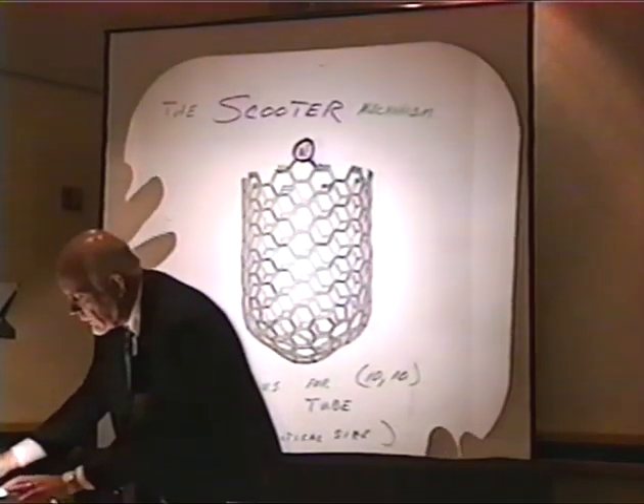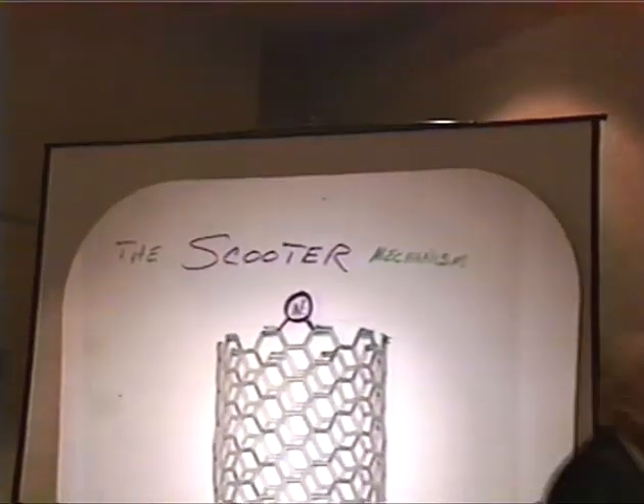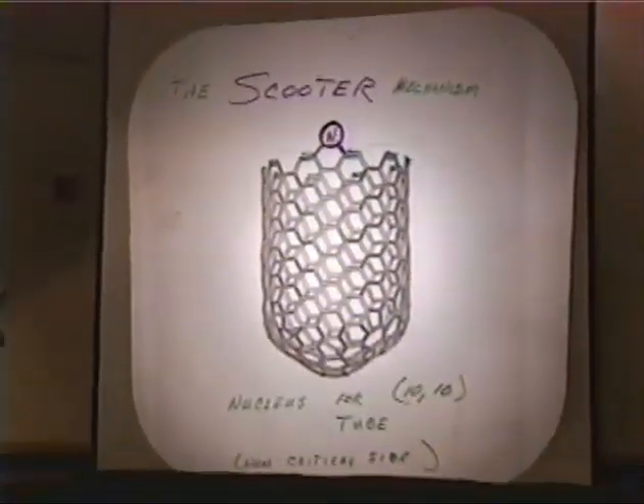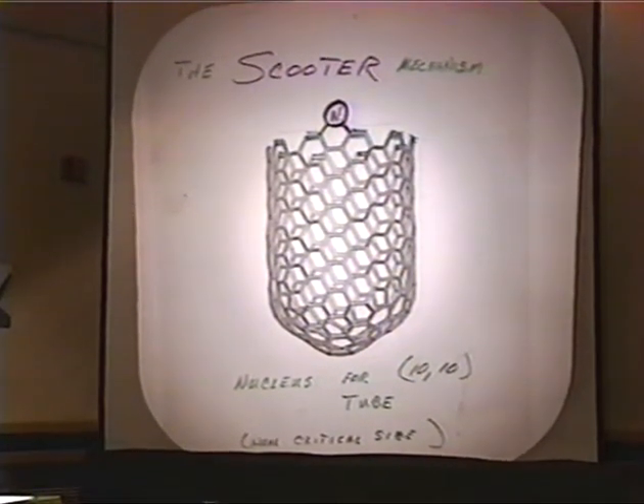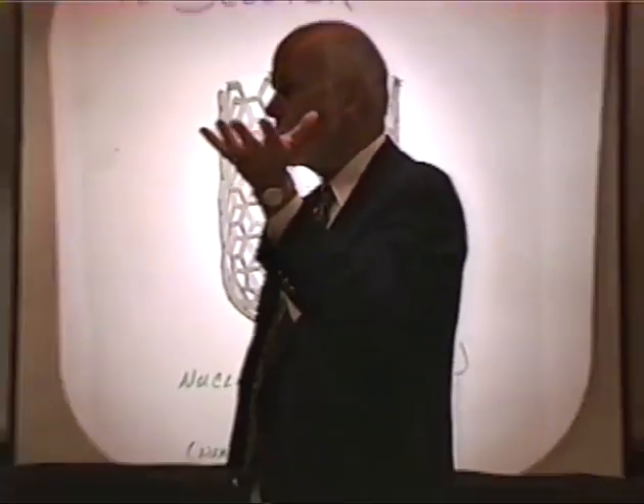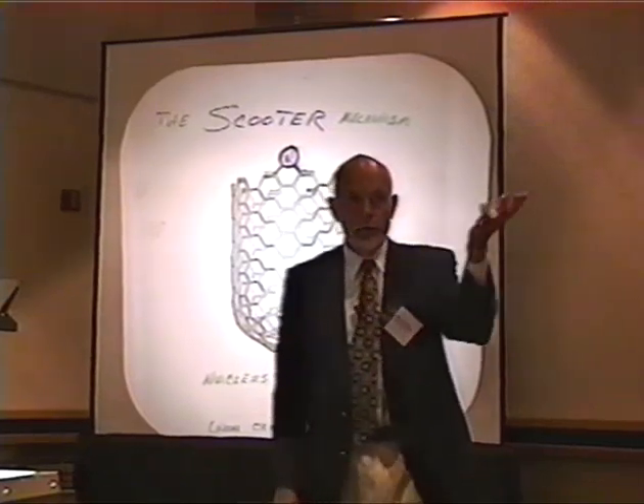And in wondering why this tube would be formed, we have conjured up a mechanism for its formation, which we gave a cute little title, the Scooter mechanism. I don't have enough time to talk about it, except to say that what we think is going on here is very much what goes on when buckyballs themselves form. Namely, you make a carbon vapor, it starts to condense, you start to get a little carbon network, mostly hexagons, a little raft growing in the gas phase, but there's all these dangling bonds on the periphery of the raft, and those are tremendously high energy for carbon. And so if the temperature is high enough that this raft can wriggle around and rearrange its bonding to try to minimize this edge area, it will do that. There's two strategies that it can use.